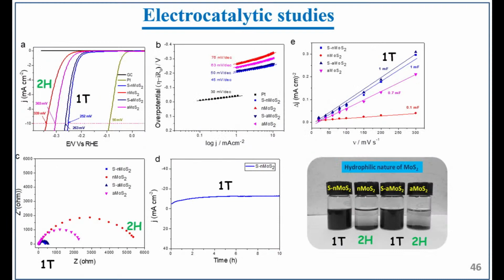So if you go for electrocatalysis studies, where you compare all of them together, for platinum it starts around 0, and for 10 milliampere it took 90 millivolts overpotential. But you can see that the 2H phases are inferior for hydrogen evolution. In the case of the 1T phase, you have 252 and 263 millivolts at the 10 milliampere current density region. Similarly, platinum produces a 30 millivolt lower Tafel value compared to the other materials, but both 1T MoS2 produce 45 and 50, while the others produce 60 and 70.